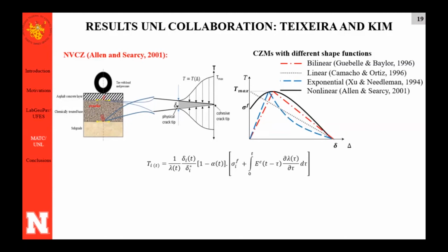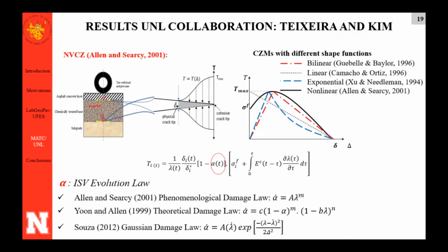We believe this model is more suitable for asphalt mixture prediction because it accounts for the viscoelastic behavior of asphalt materials by including the convolution integral in the model. But in order to use this model, we have to define an internal state variable that is going to dictate how damage propagates when cracks start. And this internal state variable can be different functions. Allen and Searcy proposed a phenomenological damage law that considers 2 parameters, A and M, to describe how the damage will propagate throughout the sample.